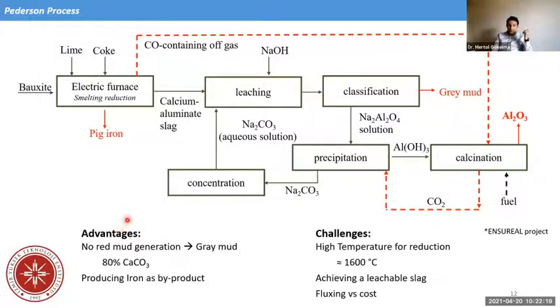There is no red mud generation, and it's called gray mud. The color red in red mud is because of iron oxide. And in this case, because we reduce iron oxide easily with carbon, the color of the mud is not red anymore, so we call it gray mud. And it is 80% mostly calcium carbonate mud. And another advantage is we have two products. One is the iron alloy, and another one is aluminum oxide, instead of one product, which is aluminum oxide.